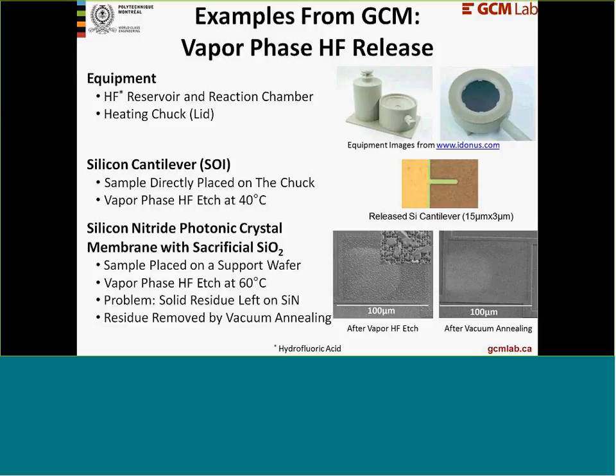Solid residue has been observed after the release. Further studies showed that the residue is the product of reaction of silicon nitride with hydrofluoric acid that is water soluble, so easily removed in wet etching. To remove this residue, the sample went through a long vacuum annealing. The results after vapor etching and after annealing are shown here.